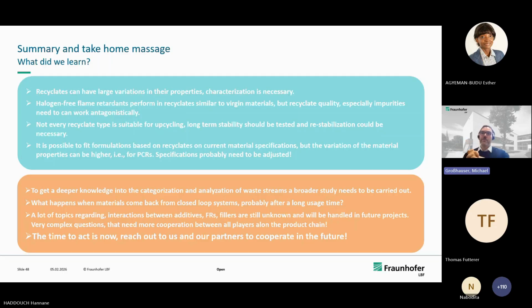Not every recyclate type is suitable for upcycling. We found out that some of the recyclates look really nice from an analytic perspective, but they are not usable for long-term stable applications. And you need to fit formulations at some point after you have characterization of your materials. And sometimes it's not possible that they fit because the variation is higher. So everyone who wants to use recyclates needs to think about whether the specifications I use are suitable for recyclates.